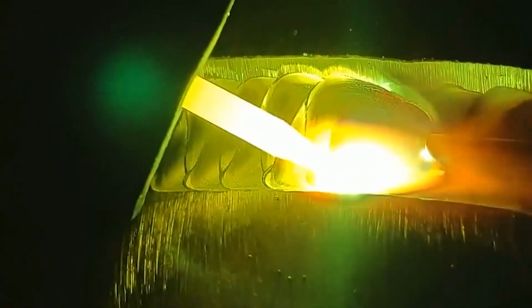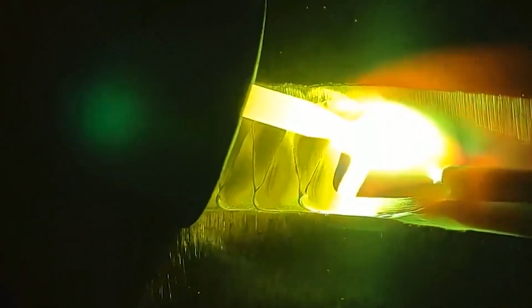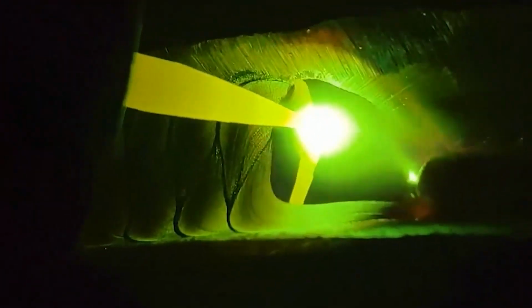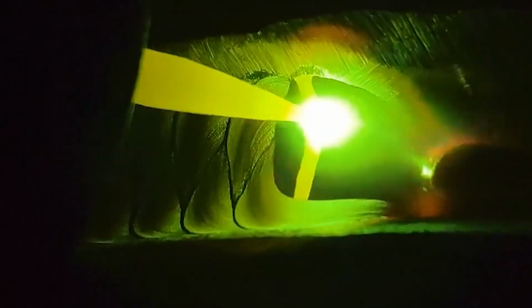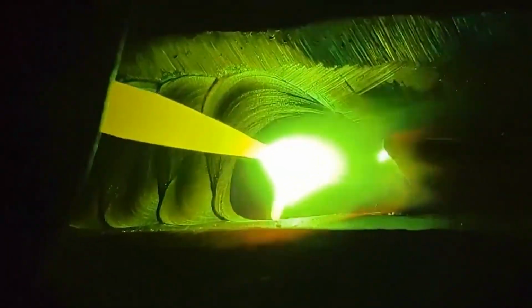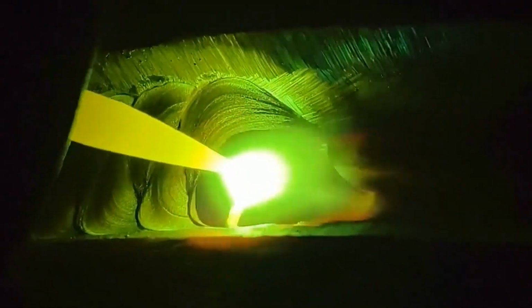The value of welding speed and argon gas flow is related to the type of material to be welded, plate thickness, and joint type. Other parameters, such as the length of the tungsten electrode extending from the nozzle, are generally 1 to 2 times the diameter of the tungsten electrode. The distance between the tungsten electrode and the weldment arc length is generally less than 1.5 times the diameter of the tungsten electrode, and the nozzle size is determined after the welding current value is determined.